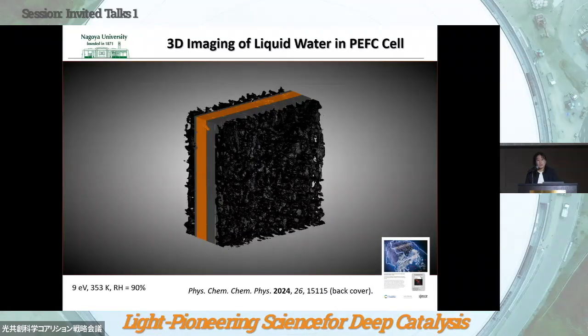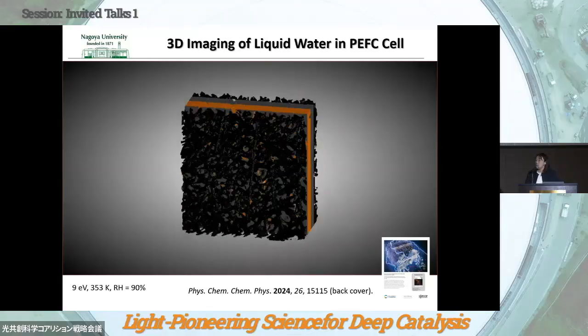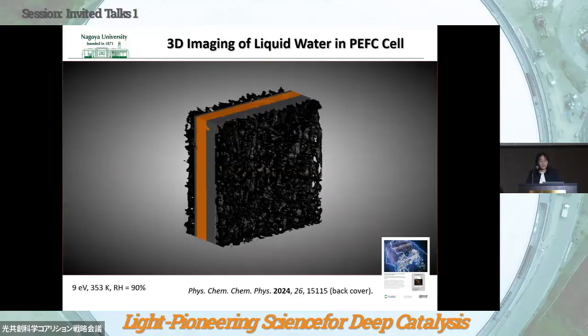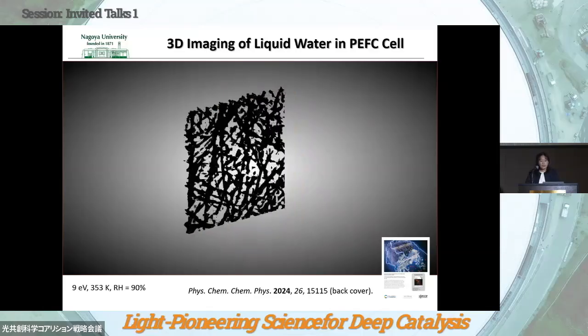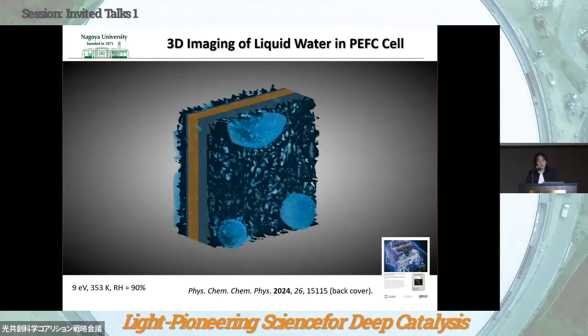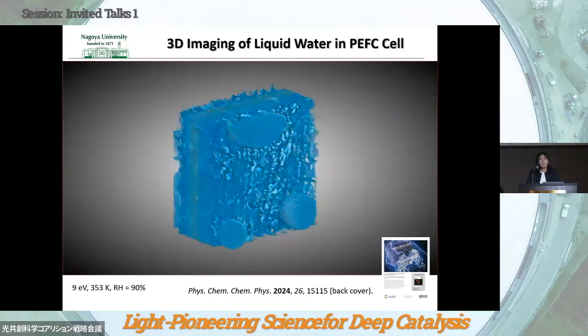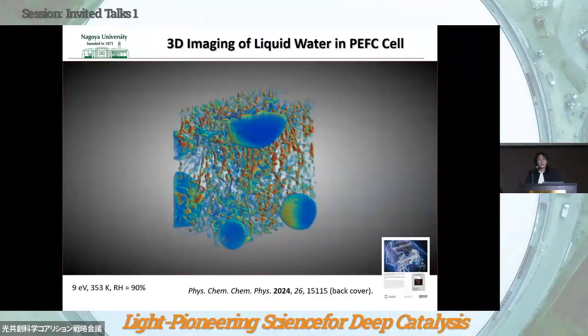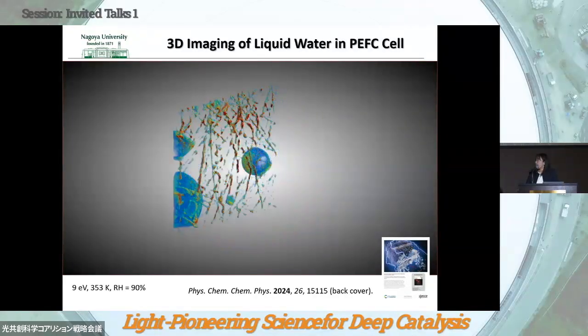And we can apply this to three-dimensional visualization. Liquid water was visualized by the X-ray CT technique, in addition to the visualization of the structure and morphology of each component. Under the humidified conditions, liquid water accumulated at various locations within the membrane. By extracting the difference in X-ray absorption between the wet and the dry state, we obtained a three-dimensional image of liquid water inside the MEA.